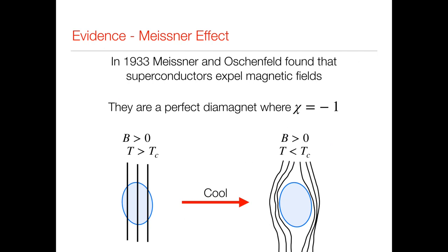The other piece of experimental evidence actually came quite a while later. Doing some experiments in 1933, Meissner and Ochsenfeld found that a superconductor expels a magnetic field. So if we start here with our sample of material, we've applied a B field, but we're above the critical temperature, so the lines of flux just pass into and through the material. Now we cool our sample down, and what is found is that when we go below the critical temperature, the sample somehow arranges itself to expel those field lines so that B is 0 inside the center. So the field inside here is 0, even though the external field is not 0.